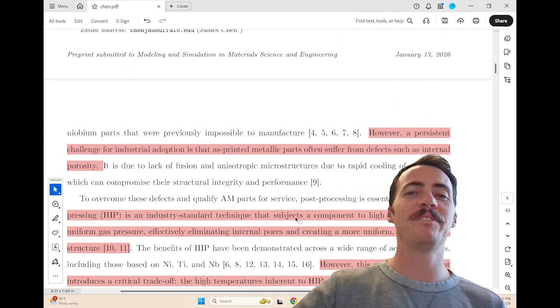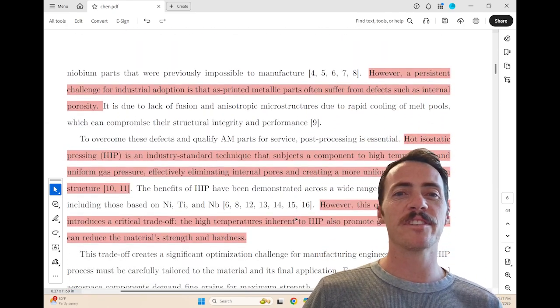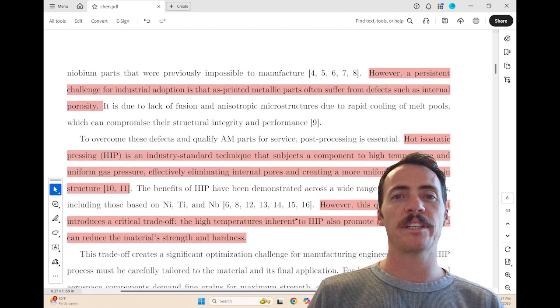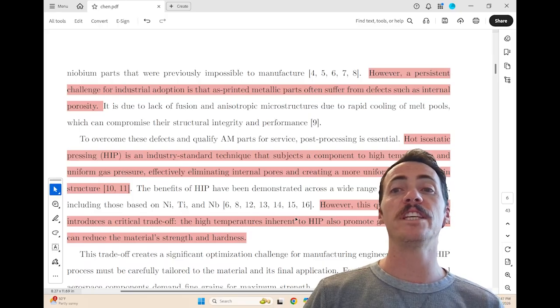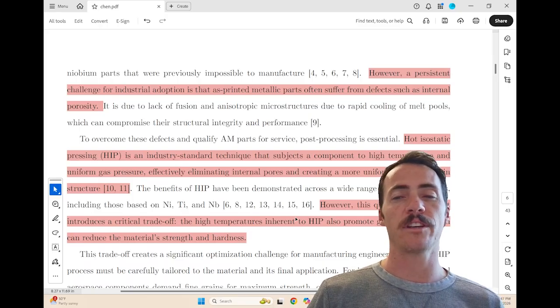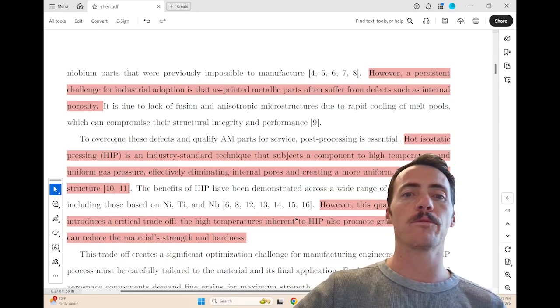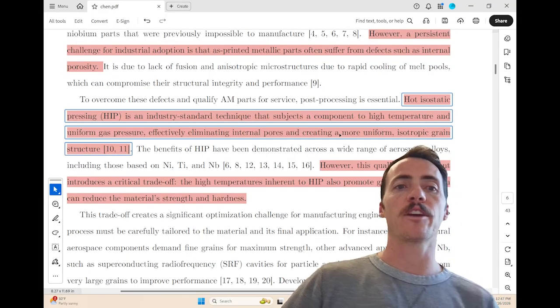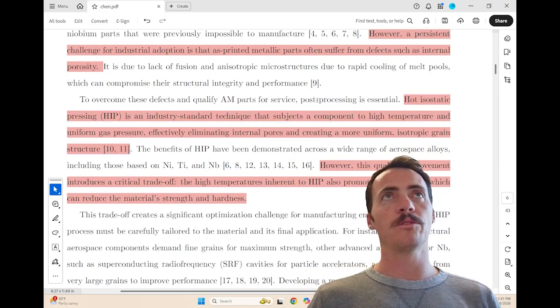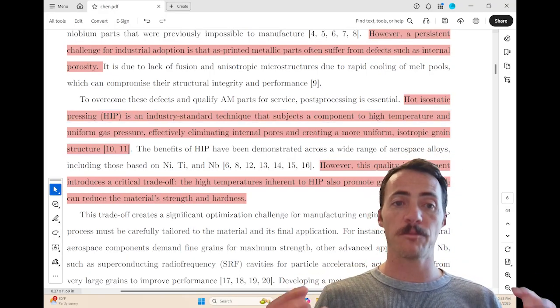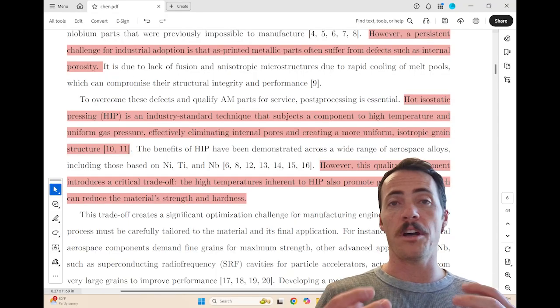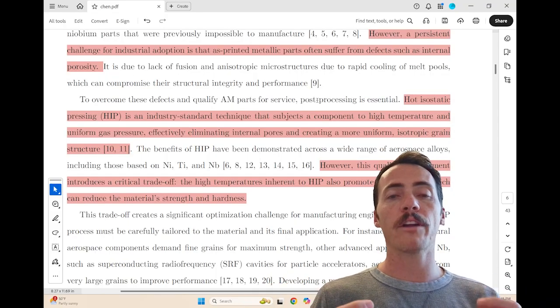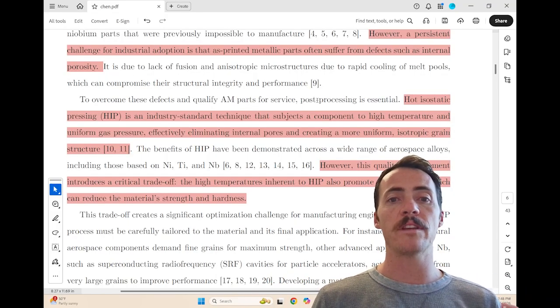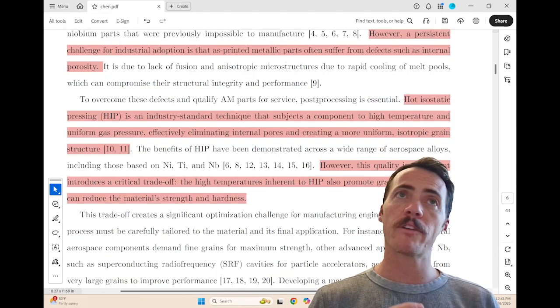But the downside, they point out here, the persistent challenge is that the as-printed metallic parts often suffer from defects such as internal porosity. And the only way that we fix those is through approaches like hot isostatic pressing, basically where you're able to apply high temperature and gas pressure on the part to essentially modify the internal microstructure. You can squeeze out these internal pores, as well as modify the microstructure.